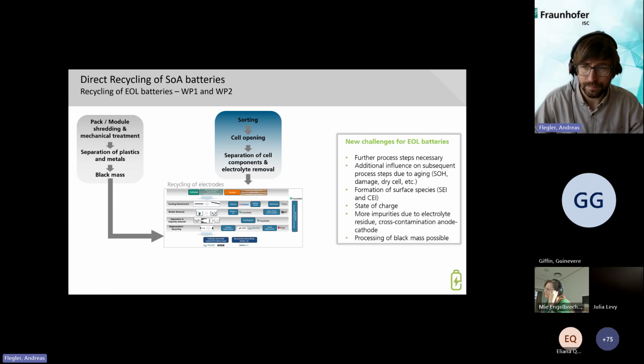We have also aged materials. Then we have some SEI or CEI on the surface, and we have to clean them. We have different states of charge, which affect, for example, the coating detachment, and we have more impurities in the black masses. And we also want to look at whether it's possible to use this black mass from a mechanical process.